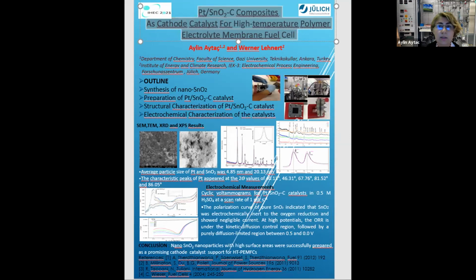the catalytic metals. This was the main motivation for me, because this study is supported by Forschungszentrum Jülich in Germany and also TÜBİTAK. If I mention my study, a nano-tin oxide activated carbon supported catalyst has been synthesized by the electrolysis deposition method for high temperature fuel cell. The catalysts of varying platinum contents were characterized using XRD, SEM and EDX. Nano-tin oxide activated carbon supported platinum as a cathode catalyst was investigated by cyclic voltammetry, electrochemical properties evaluated by cyclic